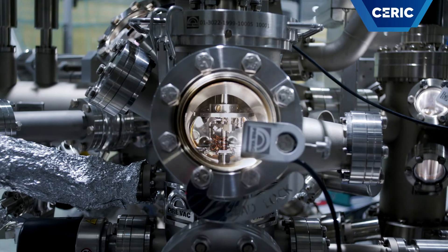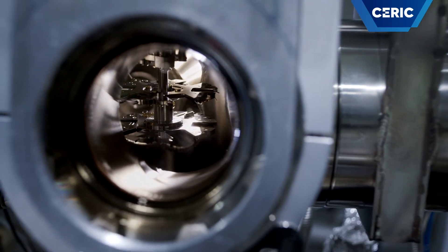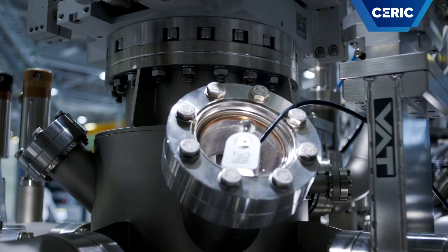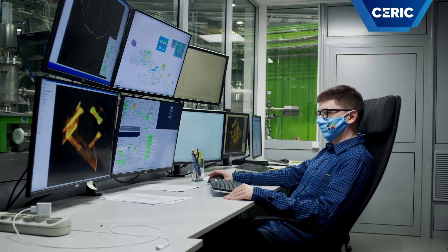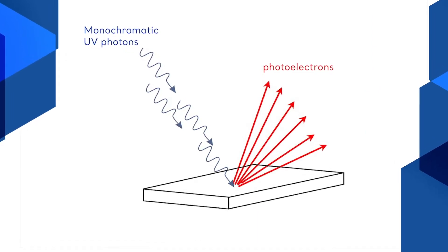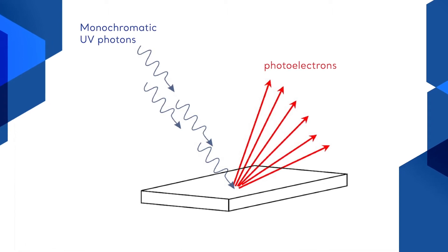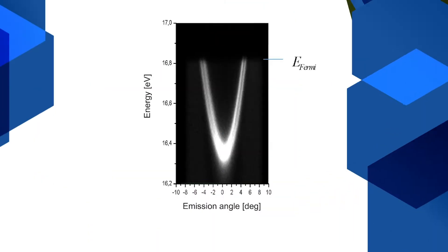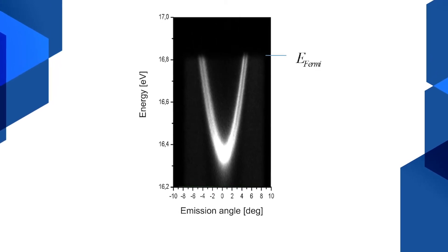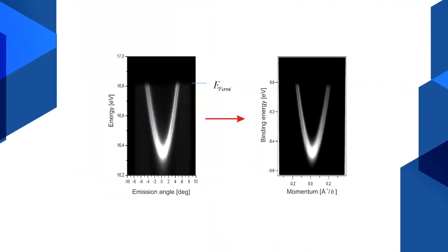The synchrotron radiation photons arrive here and photoelectric events happen in this ultra-high vacuum vessel. We can register many millions of events per second. We know that the photoelectrons have been emitted at specific angles, which satisfy both conservation rules and the dispersion relation. We measure the kinetic energy and direction of emission of each photoelectron. When many of them are collected, we draw the angle-energy distribution. Assuming the non-interacting electrons model, it is very easy to figure out the dispersion relation based on the angle-energy distribution of photoelectrons.